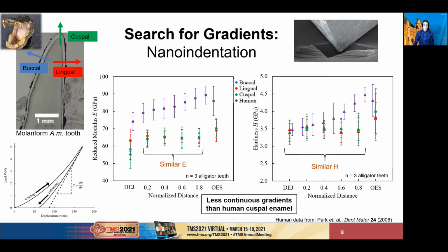The microstructural gradient was most dramatic only in the outer 30-40 microns of the enamel. The next array of indents is evidently beyond the region of dramatic changes in hydroxyapatite nanocrystal size and packing. Regardless, a harder surface layer improves the durability and wear resistance of the enamel, while a softer interior transitions to the dentin.